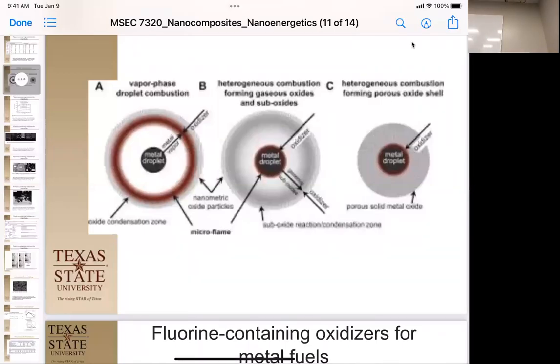So when you have low boiling or low melting materials, what can happen is that those things can then diffuse away from the burning core, and you'll have a vapor phase reaction outside of the metal droplet, okay? So in the case of fluorinated materials, you have a lot of silicon tetrafluoride as a gas and all these things. And so the oxidizer can readily continue to go in and melt the metal.